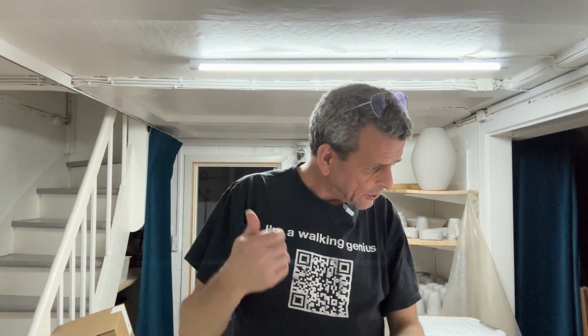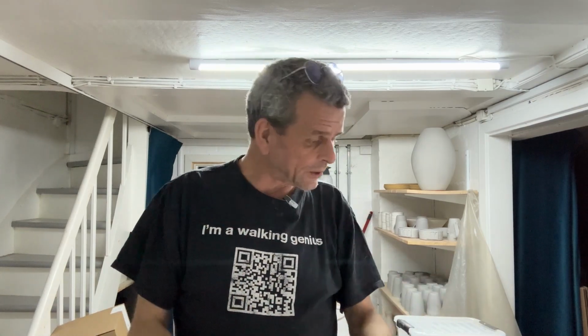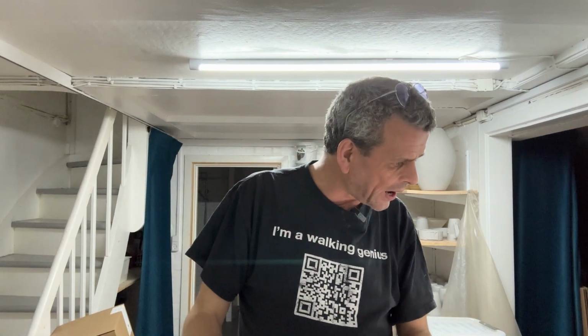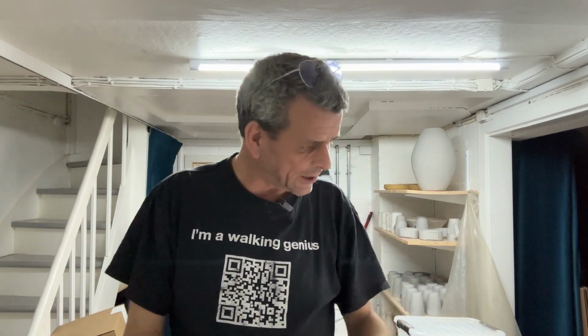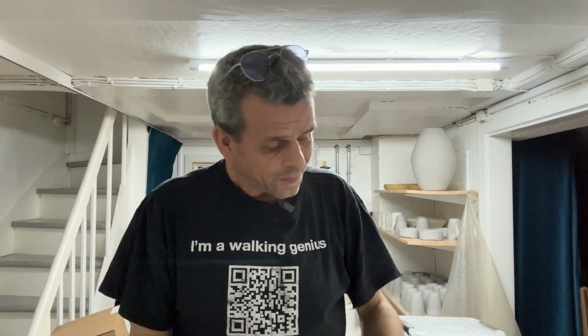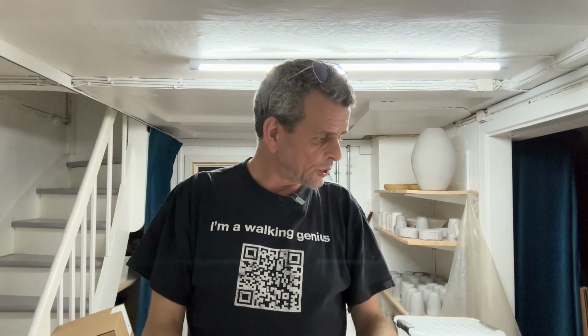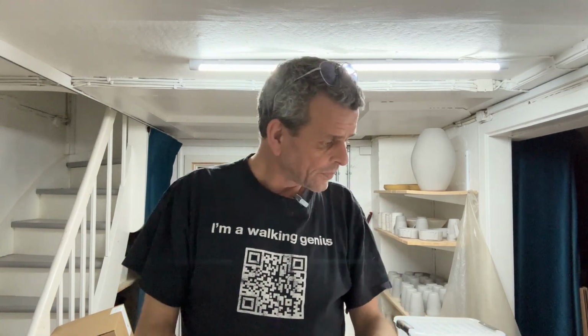So of the additives, I have a 6% rutile. That's what she added. That was not in the original recipe, and that does something great with the titanium in the feldspar and so on. And I then added the 2% bentonite that she didn't have, and then as a colorant, my difference is that I use 0.5% black stain and 0.3% cobalt carbonate. It won't be exactly the same, but I hope it will be good.